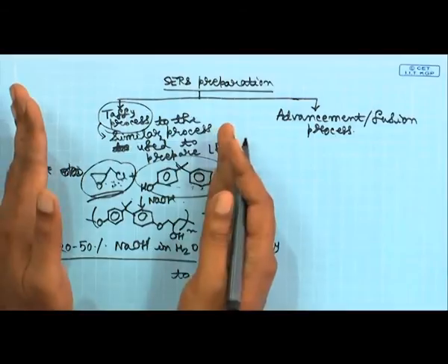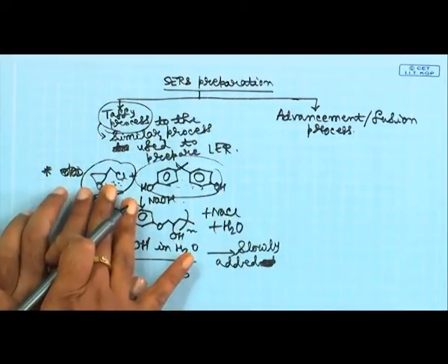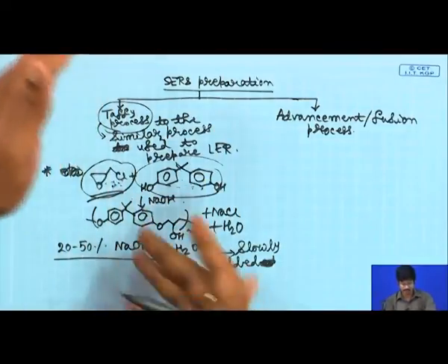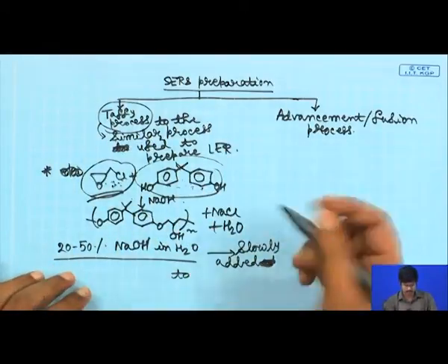Now, for the taffy process, what you do? You just tweak the ratio of your epichlorohydrin to bisphenol A. You bring it down below 10 to 1 in order to get the value of N that you want.